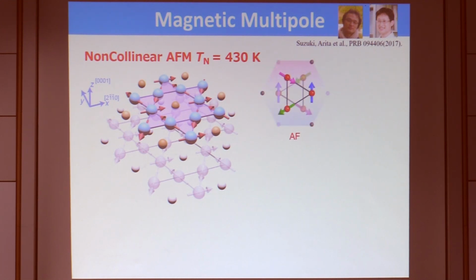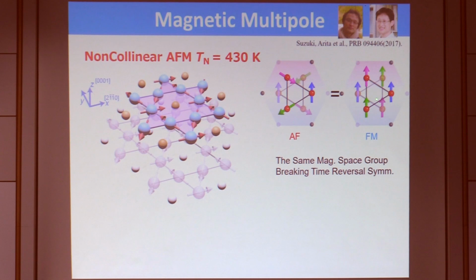If you take two triangles, which is a bilayer, it looks like this. So the total magnetization is 0. So you don't expect any Kerr effect, for example. But it turns out, if you make a collinear version of this thing, they share the same magnetic space group, and this actually has magnetization. So if you use this language of multipole, then this belongs to rank 1, just a simple dipole. And because there is an inversion symmetry center in this material, this rank 2